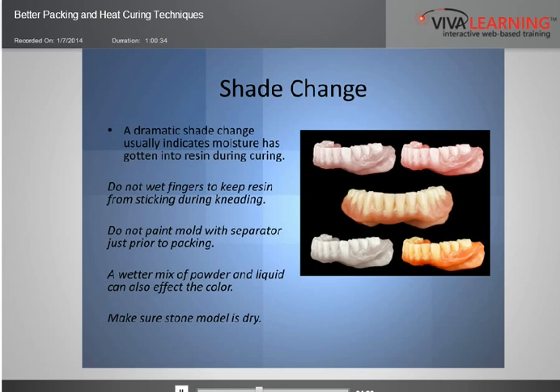Suggestions when somebody calls me on this: do not wet your fingers to keep the resin from sticking during your kneading. And I've told you this already. Don't paint your mold with separator just prior to packing. Your mold should be bone dry. That separator should be totally soaked into the surface so you have no issues in regards to moisture on that surface. You know where it'll come up? You'll have like a white film on the tissue-bearing side only. Okay, that means there's some sort of moisture on that tissue-bearing area.